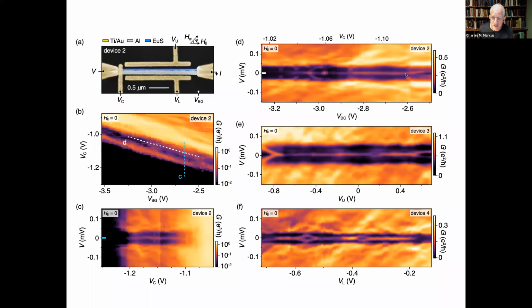What you see is for an extended range of backgate voltage, a zero bias peak. The experimental signature of a wire with a zero mode occupying this end of the wire, the other being some distance far away. Now, it's not perfect. There are many features in here where it splits and then it rejoins, and it splits and then it rejoins. We learn a lot from this.